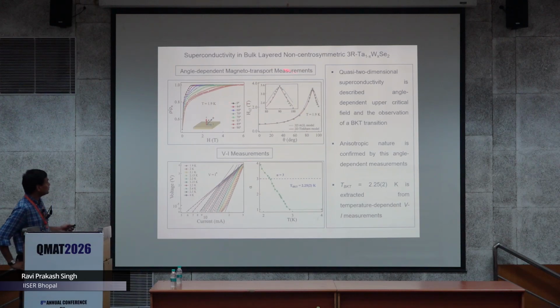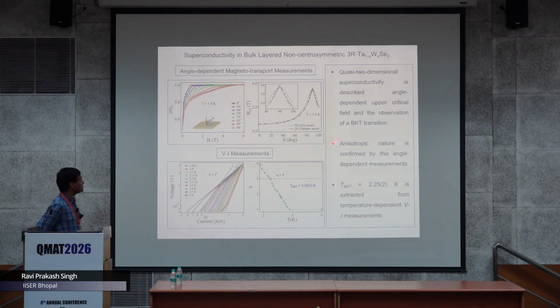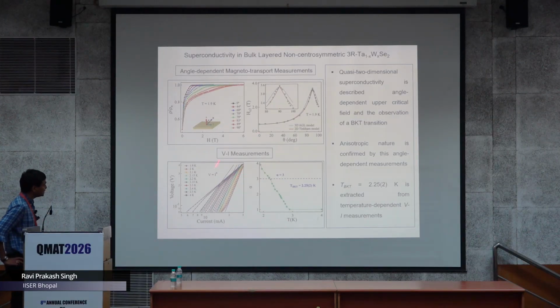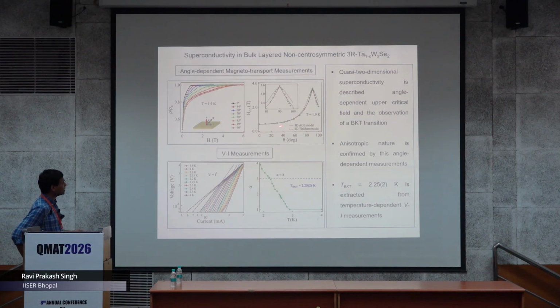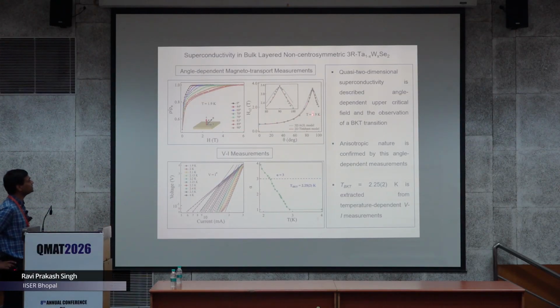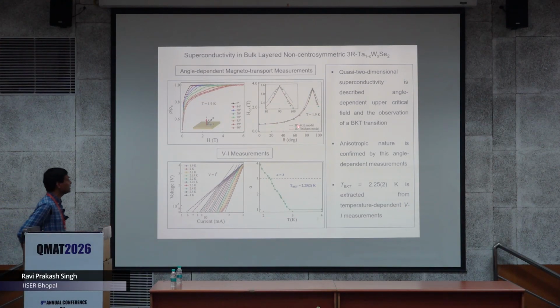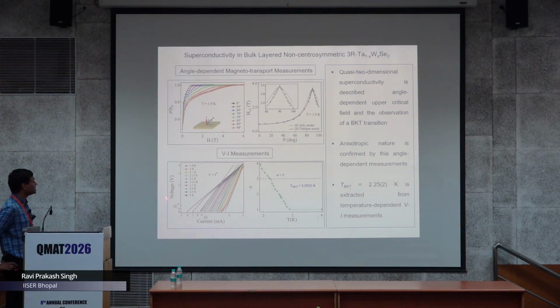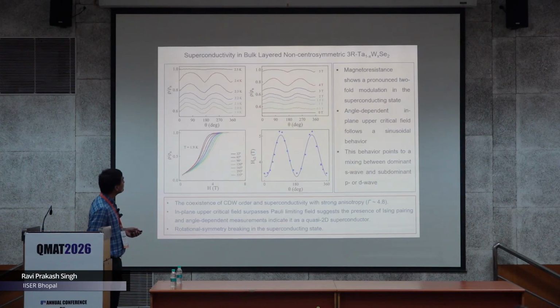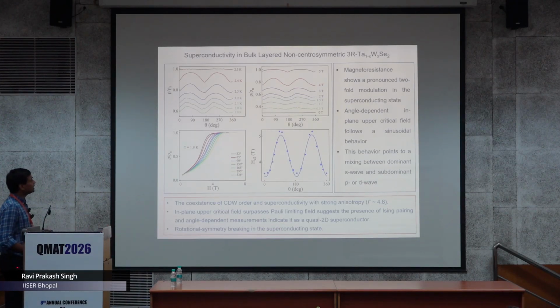An interesting thing is that after doping we are getting proper 2D superconductivity in this one, like you can see from the angular dependence measurement. We are able to see proper 2D superconductivity in this material, and it is verified by this BKT transition measurement also. And again here we are able to see the twofold rotation.